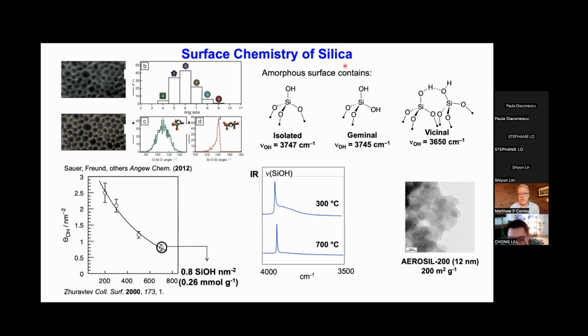We have 3 different flavors of silanol. We have the isolated silanol that is most commonly invoked in surface organometallic chemistry, a geminal silanol, and a vicinal silanol. We can control the silanol coverage just by thermally treating the silica support at a given temperature under vacuum. So the most traditional support used in this field is silica dehydroxylated at 700 degrees because it has approximately 1 SiOH per square nanometer. And the surface area of the material that we deal with, which is usually Aerosil 200, which is a non-porous silica, would give us then a loading of about 0.26 millimole silanol per gram. There are a little bit of these left on the support as well, but mostly the isolateds, and the geminal silanols generally behave like isolated silanols in reaction chemistry.